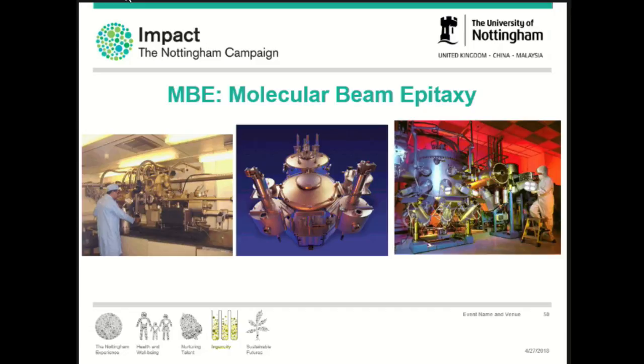Actually, this is one of the first MBE systems in Nottingham. As you can see, I didn't have too many white hairs. This was in 1985, when the UK invested a lot of money to buy these techniques, which can produce very thin films. By thin film, I mean on the order of the angstrom. Remember, 1 angstrom is about 10 to the minus 10 meters. So 1 meter divided by 10 to the 10, that's an angstrom. This technique allows you to make these films very thin, very accurately.